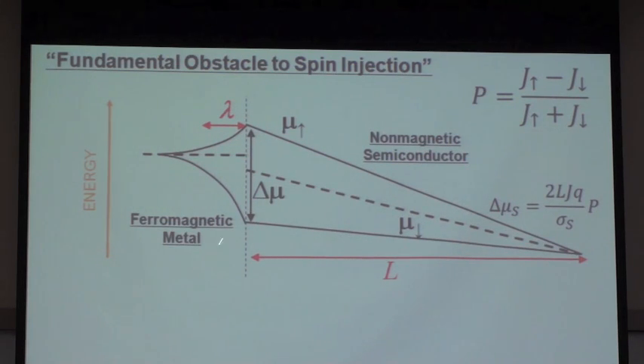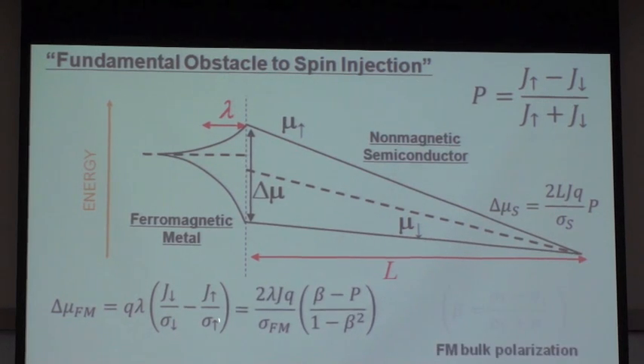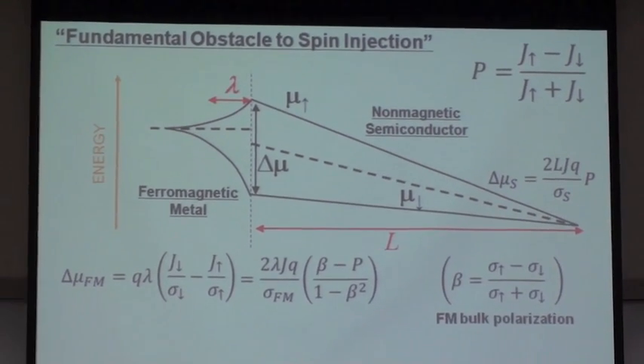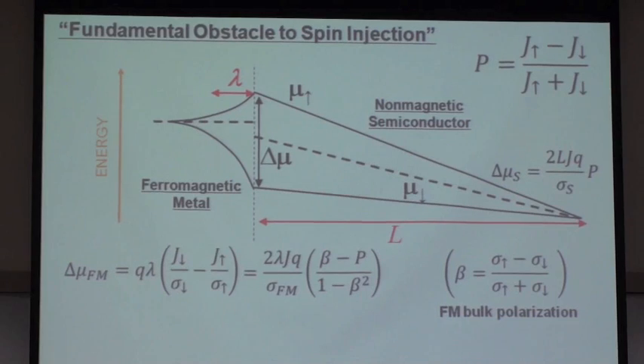Now, this splitting has to be continuous across the interface into the ferromagnetic metal, where it decays over a very short length scale due to the fact that the spin lifetime is actually very short in the ferromagnetic metal. Now we can therefore write down an expression for the splitting on the ferromagnetic side, and it's essentially driven by the asymmetry in the conductivity due to the fact that there's a difference in density of states for spin up and spin down in the ferromagnetic material.